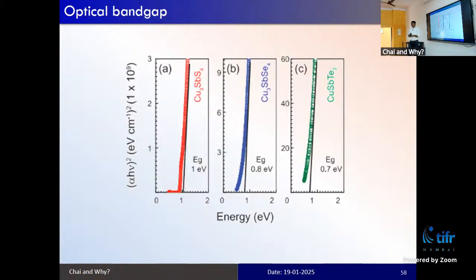So in summary, what we have done is we have synthesized copper antimony sulfide. We tried to optimize different parameters. We have grown this material using a two-stage growth process. We have optimized different conditions, and we got phase pure Cu-Sb-chalcogenide material. With this material, we have demonstrated that it can be used for solar cell applications, and we have also found that this material can be transformed from one phase to another phase by shining a laser onto it.